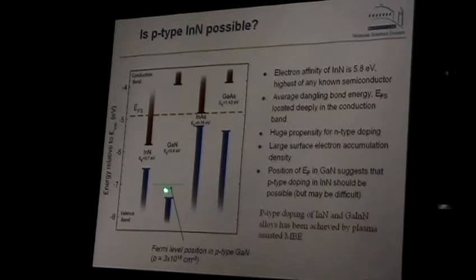So in gallium nitride it's difficult to dope, and the reason is that when you try to dope material P-type, you have to move the Fermi energy down, somewhere close to the valence band, because this is where P-type conductivity is. Unfortunately, if you start to move it from the stabilization energy, you have a bigger and bigger chance to produce defects, because once you produce a defect, it compensates the doping and you gain energy. So it's like a self-damaging process for the sample. But we know that in gallium nitride you can dope it so heavily that the Fermi energy can be here. And we thought, okay, so if we have the same Fermi energy in indium nitride, we should have P-type.